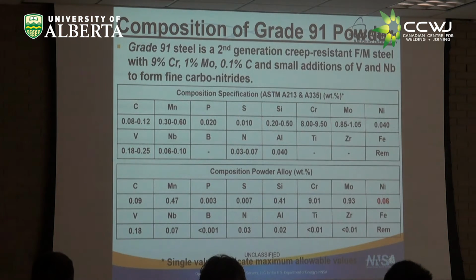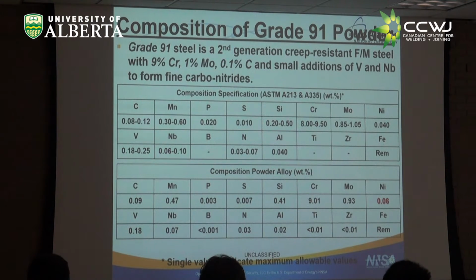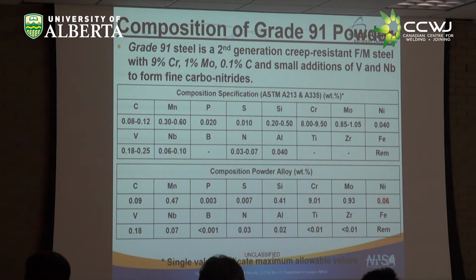The composition of grade 91, the specification is shown at the top, but basically it's a 9 chrome 1 moly, low carbon steel, with small additions of vanadium and niobium to form fine carbonitrides during tempering and also at higher temperatures. Our material, that's nickel, I think. I can't read on the screen. The nickel was a slight bit out of spec, but nothing else unusual.